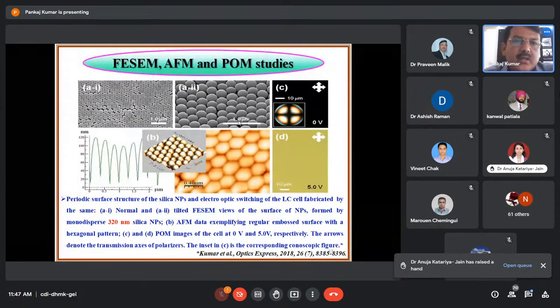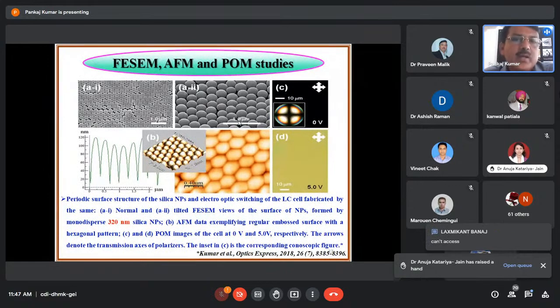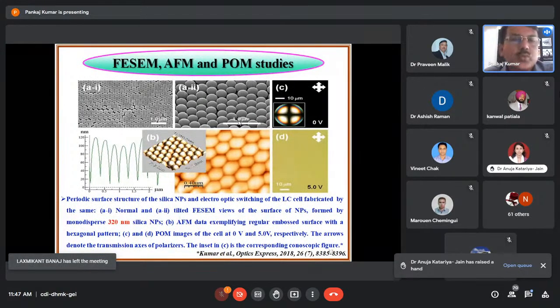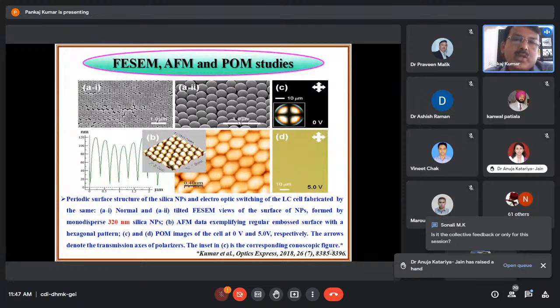A to I. A first is the normal view of the nanoparticles deposited on the glass plates. And the second one, A second, is the tilted FESEM view of the surface of the nanoparticles. And you can see a very beautiful picture of the nanoparticles. The important thing is that you can see a very homogeneous size of the nanoparticles here. These are monodispersed 320 nanometer silica nanoparticles.